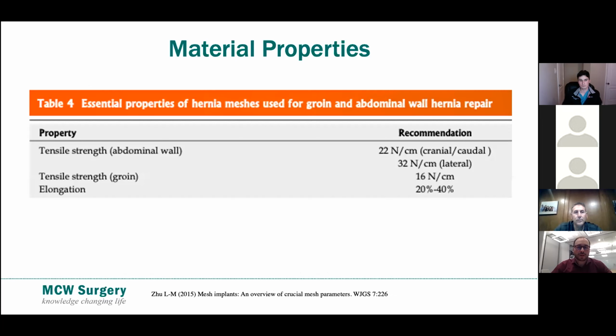But once the mesh is created, what properties does it need to withstand in terms of the physiologic strengths of the abdominal wall? It's recommended that all of these tolerate a 22 to 32 newtons per centimeter force of tensile strength on the abdominal wall, and slightly less for the groin. And I think pretty much all of the meshes that are available to us have a burst strength of that, at least when they're ex vivo. There are some studies that have shown that, at least with the lighter weight meshes, there is some decrease in tensile strength over time when implanted in the abdomen, but all of them still withstand the tensile strength required of the abdominal wall. And then elongation or elasticity, once we get into discussing some of the heavier weight meshes, do have less elongation or elasticity compared to the recommendations, but whether that's affecting the patients down the road is still to be determined.